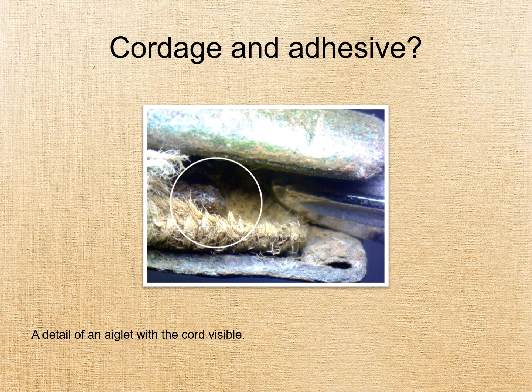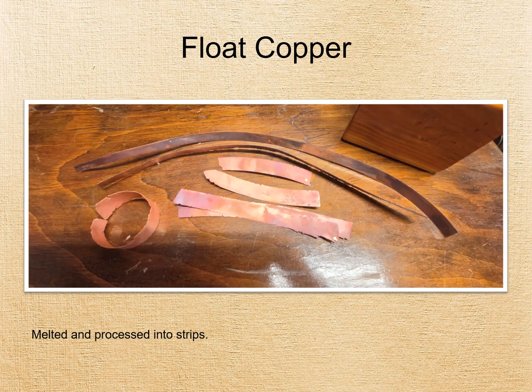In my experiments, I used cotton shoelaces and gum arabic as the adhesive to help stiffen and hold the cord inside of the aiglets. Native float copper from Michigan State was used to avoid any possible contaminants or alloys from using recycled copper. Confounding variables need to be addressed in every experiment. I should have forged this metal out with a hammer and an anvil, but I have a damaged shoulder, so I used a rolling mill to process this metal. I do not feel this would drastically alter the results.